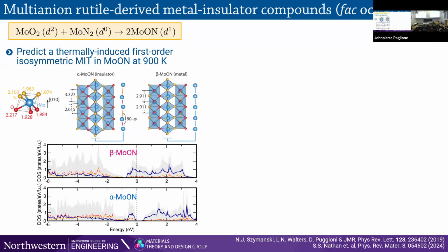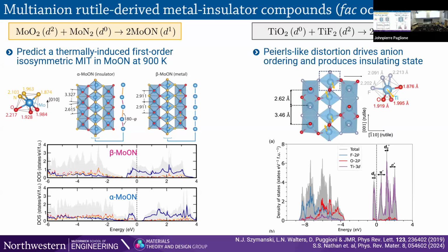They're on opposite faces. In mixed anion materials, and there's a lot of materials chemistry that goes into it, this FAC configuration is the stable configuration for the local unit. And these materials do order with this geometry over some length scale. This system is being synthesized in thin film form. It's actually much more difficult to make this as a bulk single crystal. And over several nanometers, you can see this order. But beyond that, it disorders. Okay, so there's the length scale problem to that order.